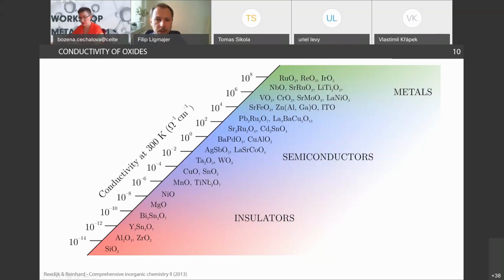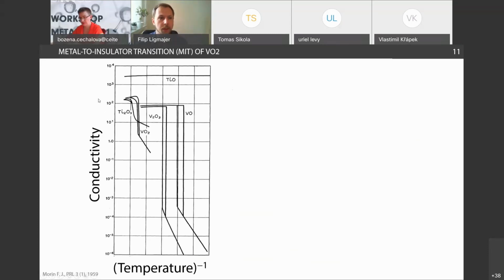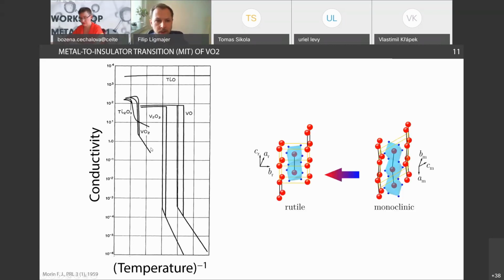And VO2 is interesting because it can undergo a metal to insulator or insulator to metal transition as you go from low temperature to high temperature. Here is probably the first mention of this property, where it's already from the late 50s of the last century. And here is reciprocal temperature on the x-axis and conductivity on the y-axis in logarithmic scale. So low temperature is on the right and high temperature is on the left. There are also other oxides which have similar behavior, but VO2 is nice because it undergoes this transition around those 70 degrees Celsius, which is related, or this behavior is related to its structural transition.